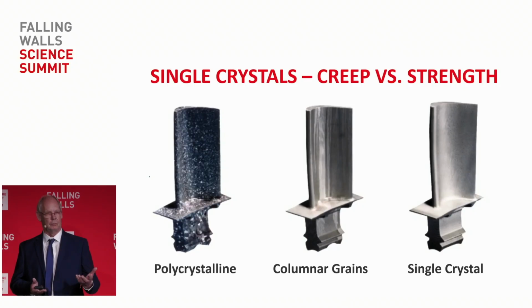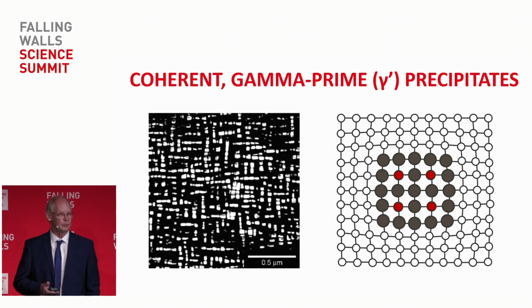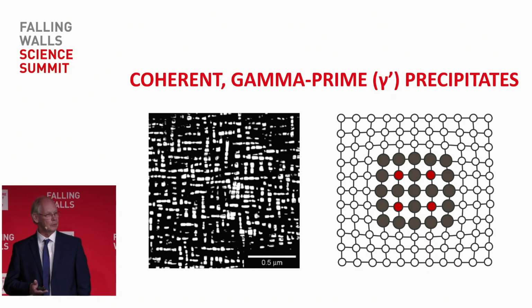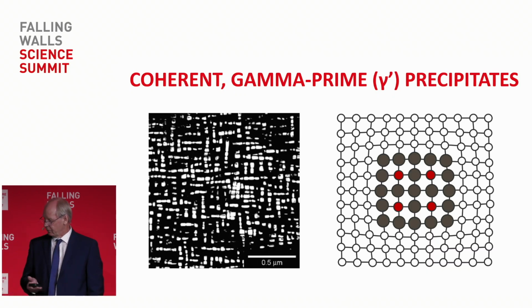That's a very major property of these materials. The main source of strength in a nickel superalloy is this. In metallurgy, it's a very famous phase. It's called gamma prime. It's an ordered intermetallic alloy of nickel-3 aluminum. And the picture on the left shows the blocky structure it has.